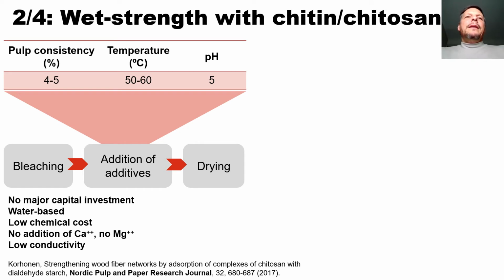In the second case, I explained the development of wet strength. And here I once again use a natural polymer, either chitin or chitosan, deacetylated chitin. This is an option that has been explored in paper making. In fact, chitin and chitosan products have been used in the past in paper making. And here I just highlight in this slide the fact that the use of this type of additives is quite demanding if you think about the different conditions that they need to sustain and the very narrow window of operation as far as the consistency, temperature, and pH, and conditions in processing like low conductivity and the fact that we want to minimize the cost and it has to be water-based and minimize capital investment. These are really very challenging situations.